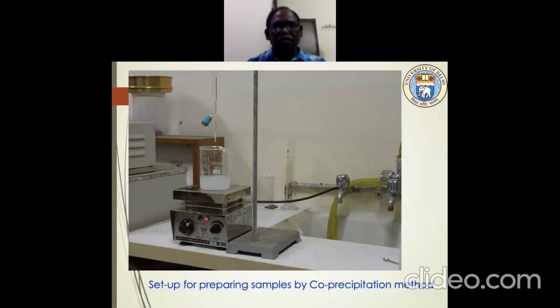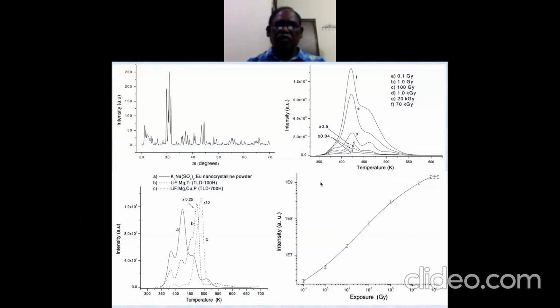I have not taken the very good nanoparticles; we have found sizes of the order of maybe 20 nanometers. This shows again the XRD, and it matches well with the literature. These are the glow curve structures, and they don't change much because there is no phase transition, so they don't change much in this temperature range and with different doses. And this again is a comparison with the commercially available phosphor, and I can see that they are very, very much comparable. But the more important thing over here, you can see, is the dose.